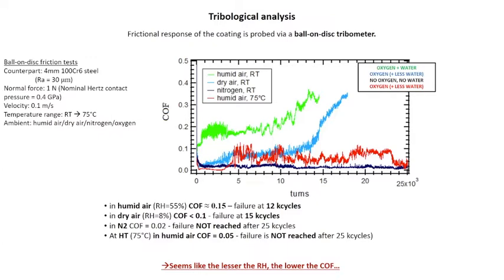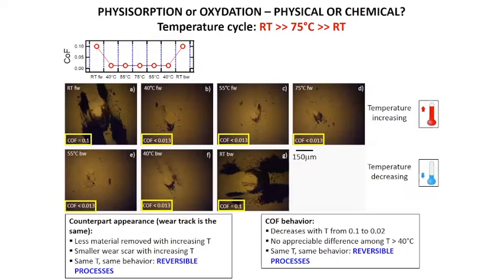In order to deepen these aspects, we repeated similar experiments. In this case, we checked the coefficient of friction and also the appearance of the ball counterbody at different temperatures. So we start at room temperature, we move to 40 degrees, 55 degrees, 75, and then back to 55, 40, and room temperature. So we did a cycle in terms of the temperature of the coating. What you can see is that the coefficient of friction started at 0.1, and then it drops to 0.01, 0.02 at the higher temperature here. And then we restore again the initial value of the coefficient of friction when we go back to room temperature.